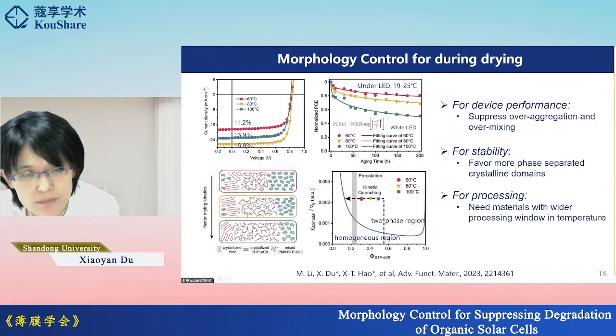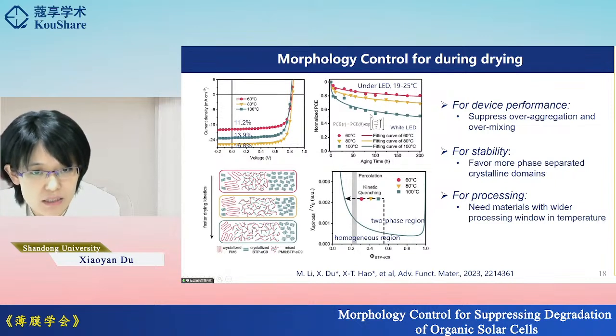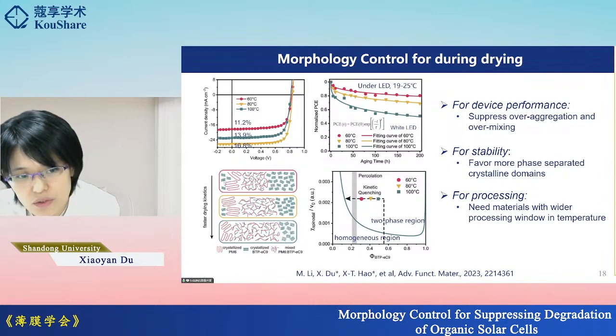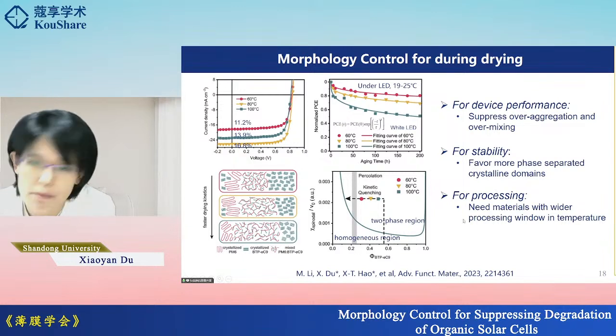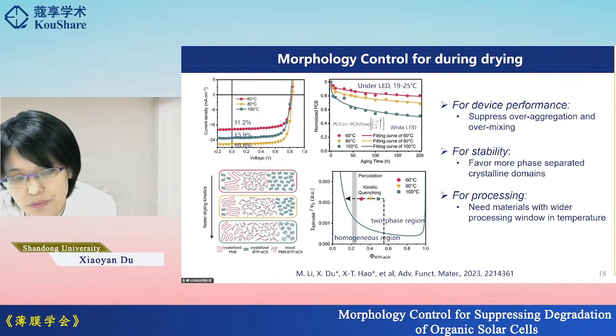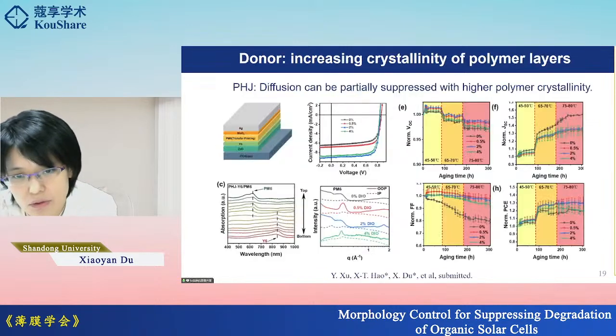But for stability, we need the opposite, which favors more crystalline, more phase-separated domains. And for processing, we need materials that are not so sensitive to the processing conditions, for example, the coating temperature and the coating speed. So for materials development, these three aspects need to be balanced in order to improve performance, stability, and also processability.